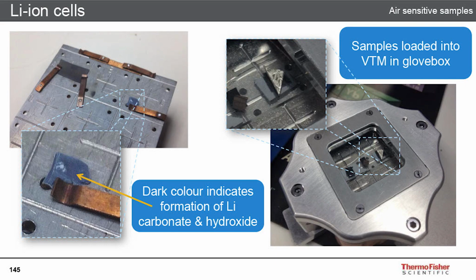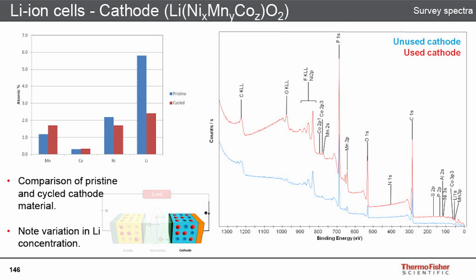lithium-ion battery materials. So here's just looking at two cathode samples, one not used, one used. And one of the nice things about XPS, it's one of the few techniques that's able to measure lithium relatively easily. It's got a weak signal, but as Manish showed this morning with the lithium fluoride powder, if we can access the material, we can measure lithium, which is quite tricky to do with other techniques like EDS. So here, between the pristine sample and the cycled sample, we can see there's more lithium at the surface in the pristine sample. After cycling, we're seeing less lithium, and that's partly due to the formation of this SEI layer, which is kind of what reduces the capacity of the battery because it limits the ability of lithium to transport from the electrode through to the other electrode.